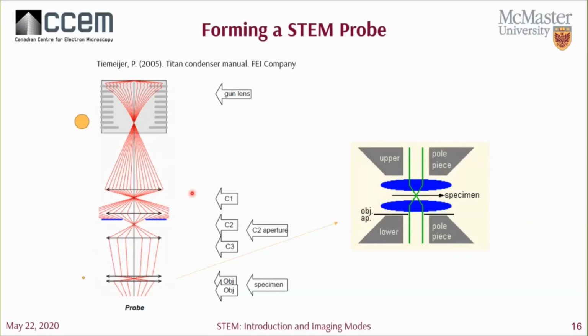So in the Titan, we have a 3 condenser lens system. The probe is also formed using a C2 aperture, and that helps define the convergence angle of your beam. And we have here a set of twin objective lenses shown here, in which the upper pole piece is strengthened to converge our beam into a point on our sample.